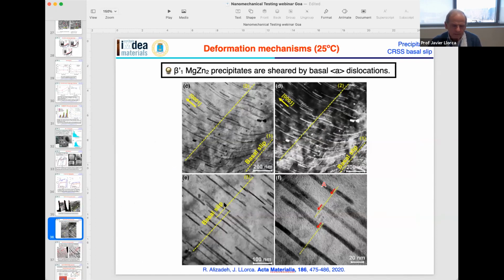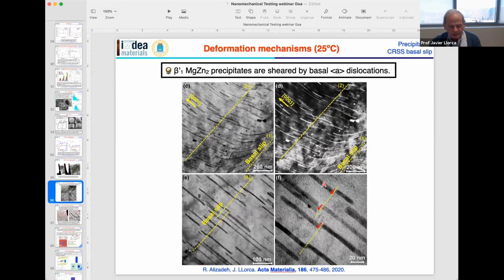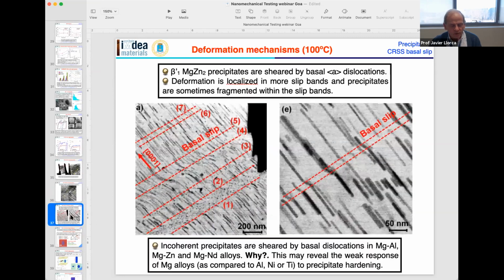These are the traces of the basal plane, and these are the precipitates. You can see very clearly, like in this case, that basal dislocations have been able to shear the precipitates. This is what happens at room temperature. But if you go to high temperature, the effect is exactly the same. Sometimes in some regions, the basal dislocations have completely destroyed the precipitates. This was somehow surprising because normally these precipitates are incoherent, and incoherent precipitates are normally not sheared by dislocations in other metals, but in the case of magnesium, these incoherent precipitates can be sheared by dislocations.